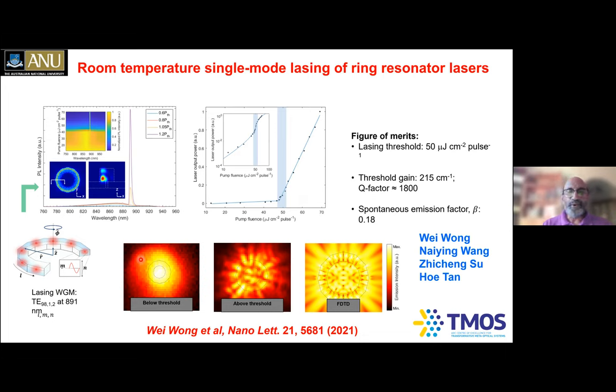Below threshold, you see a broad light emission, and you can see the broad spectrum below here. Above threshold, you see very narrow line width, and also these whispering gallery mode lasers. Ring resonators typically end up having whispering gallery modes. In fact, these are the measured whispering gallery modes and the theoretically calculated ones. They match very well. Again, these are room temperature operating.